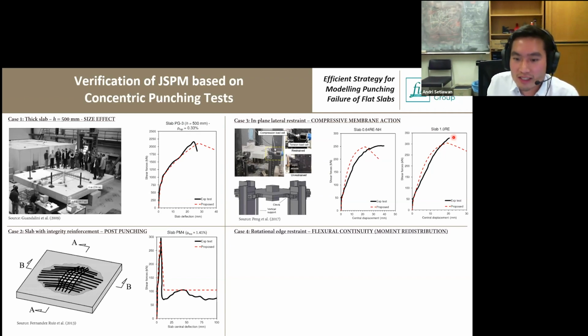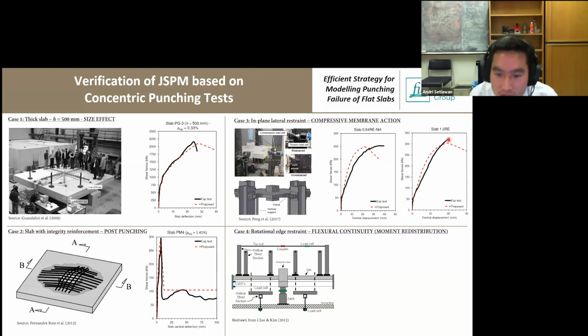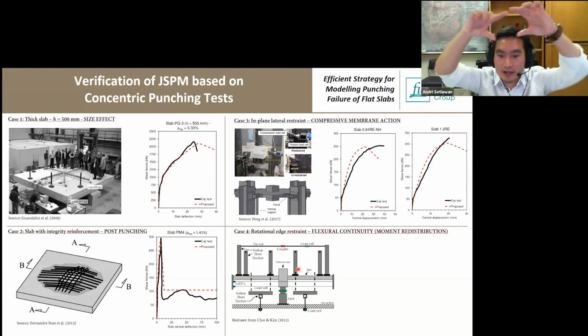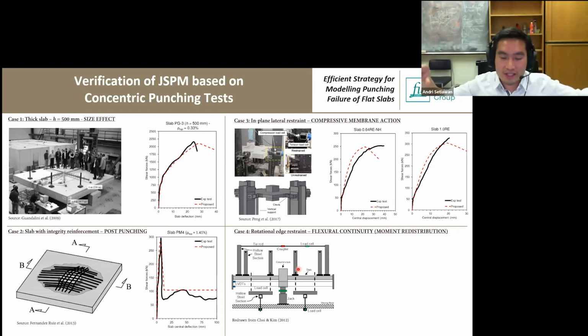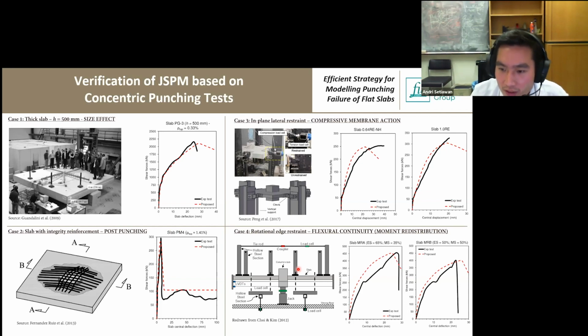The last one is the slab with flexural continuity. This is quite a unique test setup where we have isolated slabs, but we have a steel frame system which introduces a sagging moment. So instead of only a hogging moment region, with this typical test setup, you also have a sagging moment along the edge. We are testing these 2 slabs with different reinforcement proportions in the midspan and in the end span, and we are able to capture both scenarios accurately, both the load rotation and also the failure, which means that we are capturing the moment redistribution accurately in the model.